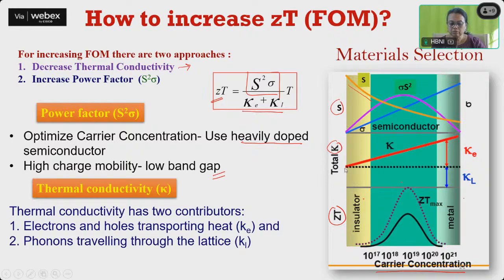Now coming to the thermal conductivity part. So if this is the lattice thermal conductivity and this is the electronic thermal conductivity, it keeps on changing. So for an insulator, the maximum thermal conductivity is because of the lattice, and in metals the electronic part is also playing a part. And then we come to the ZT. So we see that ZT is maximum, ZT max, for any given material with a charge concentration of around 10 to the power 19. So that is a heavily doped semiconductor.